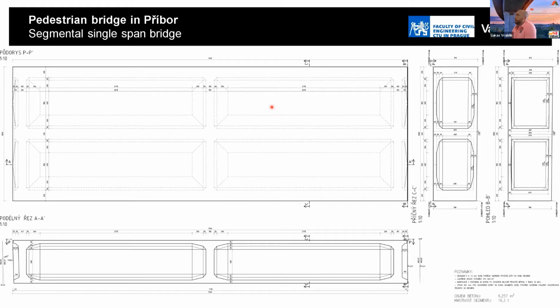This is the shape of the typical segment. It is something like a box with hollows, with one intermediate cross beam, and also the same cross beams were used in the outer area of the element. In the joints, it was important to reduce the cross-section area, because, as I said, we have to satisfy the condition for the stress in this joint during the service life of the structure. So if you reduce the cross-section area, you reduce the number by which you divide the stress, especially the normal stress, the effect of the axial force of the prestressing. So then you obtain a little bit more benefit of the prestressing in this area, and it was important.